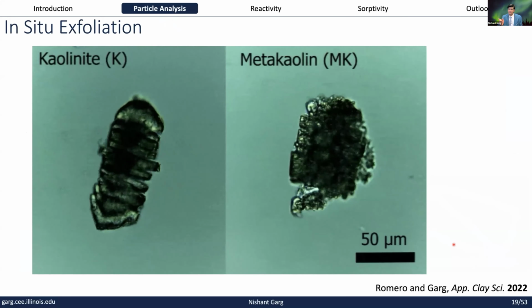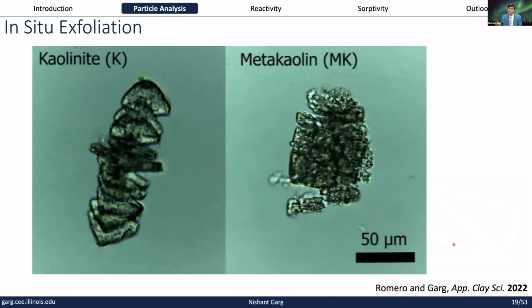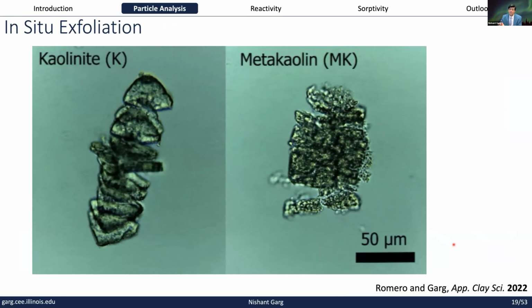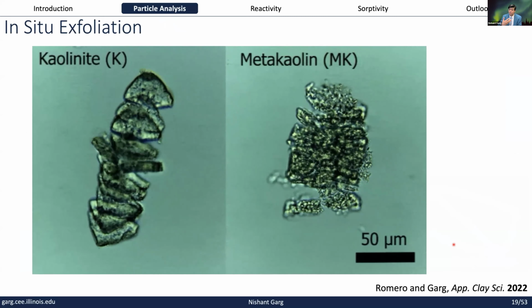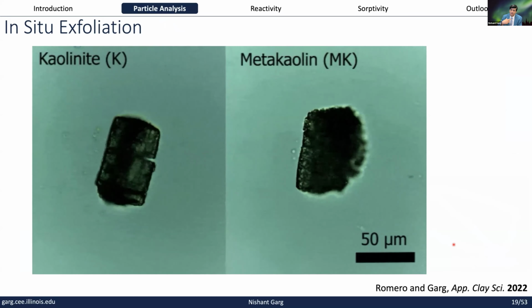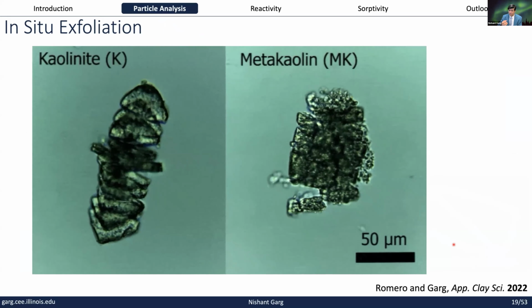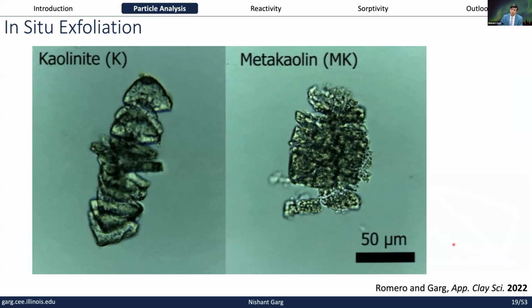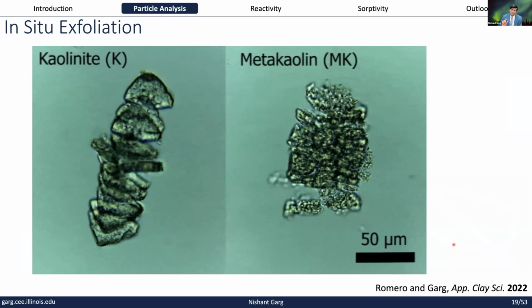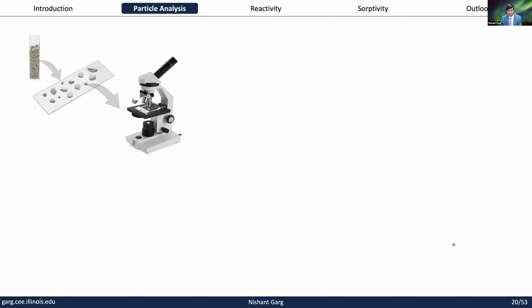But what we find interesting is that even your metakaolin does that to some extent, even though that layered structure has been changed due to the calcination. So what this really means is that it has a lot of internal porosity, which takes in that water and affects water demand. So now we have that evidence by looking at the single particle.